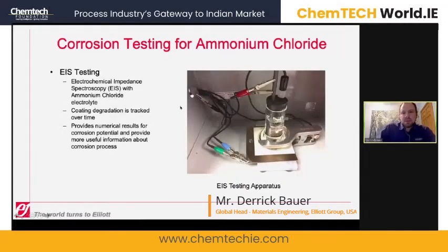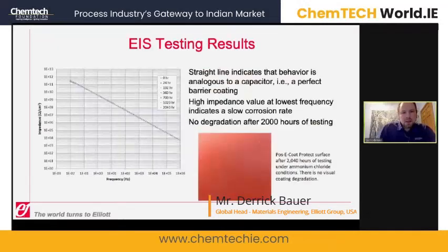We also performed corrosion testing, where ammonium chloride solution was placed into this tube. This utilized electrochemical impedance spectroscopy, which is the only method we could come up with to give a numerical value to the corrosion resistance of a coating. So what is measured during this testing is the capacitance behavior of a coating. Essentially, a good coating will act as a perfect barrier between the environment and the substrate that it is placed upon. That will effectively stop all corrosion.